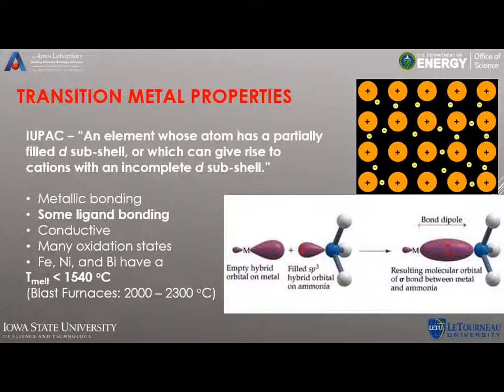Now, the specific metals that we were looking at were nickel, bismuth, and iron, and then there's also copper as well. But the nickel, bismuth, and iron all have melting points below 1,540 degrees C, and that's quite a bit lower than the temperatures that blast furnaces reach. Blast furnaces provide the standard method for reducing these metals.